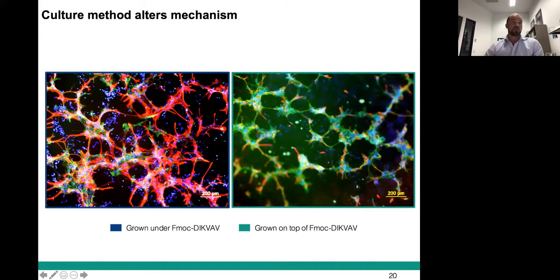I'm just showing a picture here of a pseudo 3D model. So basically you put the astrocytes on the bottom, you cast the hydrogel on top, and then you can deliver your molecules within that hydrogel. You can see that cobblestone morphology, but we can mix them within the gels also. They're a lot harder to image, but I think you can see this sort of three-dimensional cobblestone morphology now of nearly like an organoid structure within the brain.